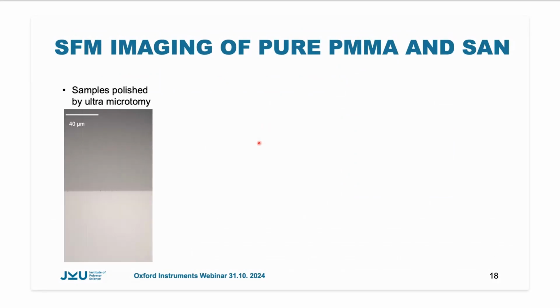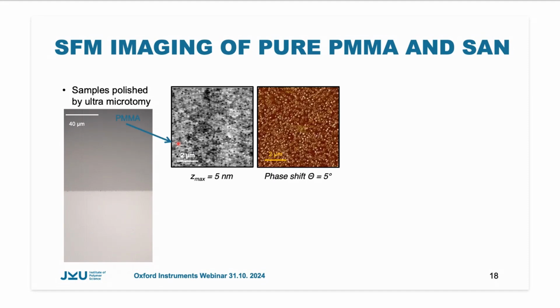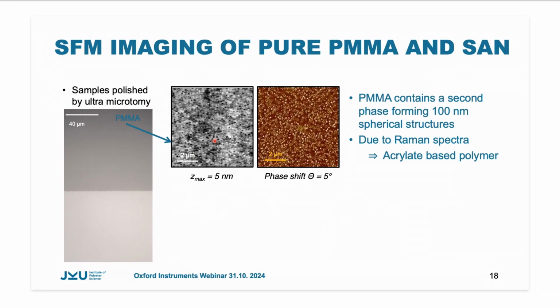Here are AFM images of our pure materials, PMMA and SAN. The samples we used are the ultramicrotomed, polished surfaces, but now we do not investigate the interface, but the bulk region. And what we found for the PMMA was not, as expected, a very smooth surface, but we found in the PMMA a second phase consisting of spherical structures with a diameter of about 100 nanometers. Since the Raman spectra do not show any additional polymer bands, we assume that it is an acrylate-based polymer which has been added to the PMMA to improve its processing conditions.